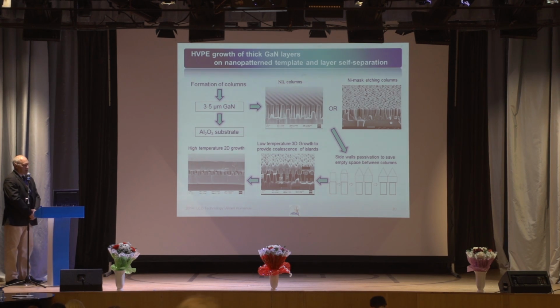And one of these methods uses nano imprint or nano lithography, where we form a row of columns somehow during the growth of the gallium nitride layer. In this case, internal stresses will not be transferred from the substrate to the top layer, and even more, the presence of such columns can be used for self-separation of the gallium nitride layer grown by, for example, HVPE techniques. This is hydride vapor phase epitaxy.